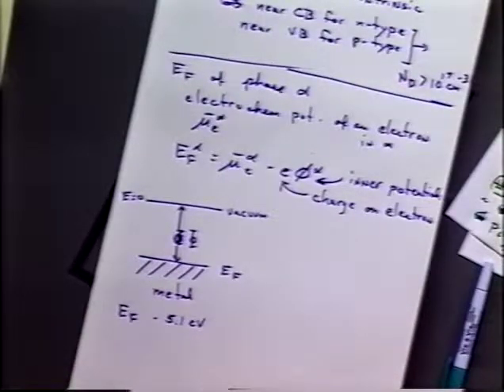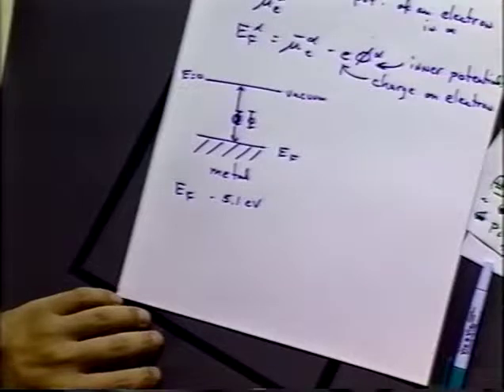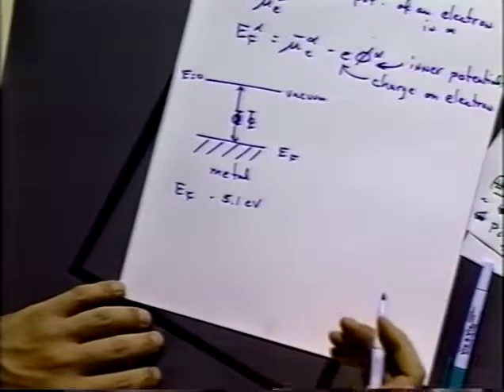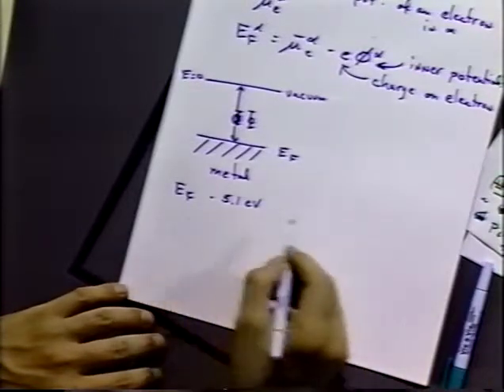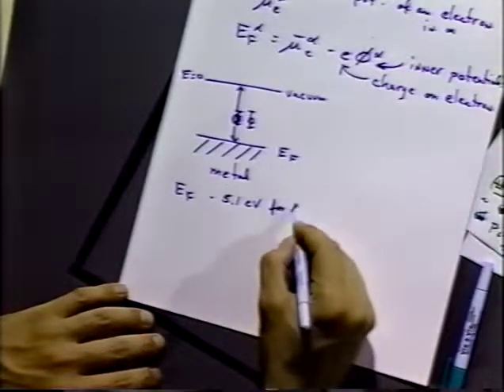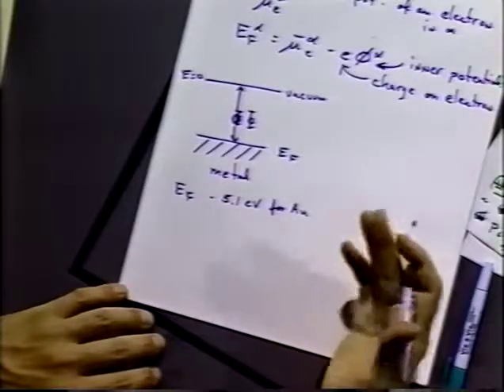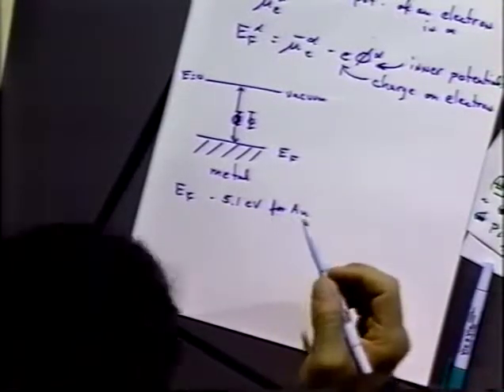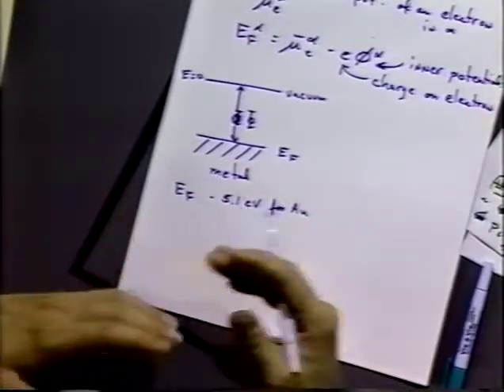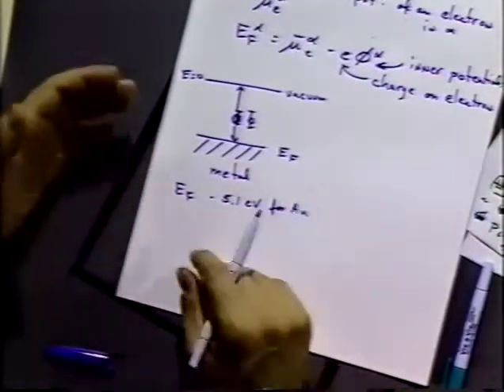Now, because we know the band gap of our silicon, we can do calculations. I can't do the calculations, but people can do the calculations. And for metals, I think it says about minus 5.1 eV, which means that the energy of an electron in the metal is less than in the vacuum, which is what you'd expect. You don't see electrons being present normally as a gas in a vacuum. If they're present, they're collected all in the metal. So they're not being sputtered off by the metal into the vacuum normally.